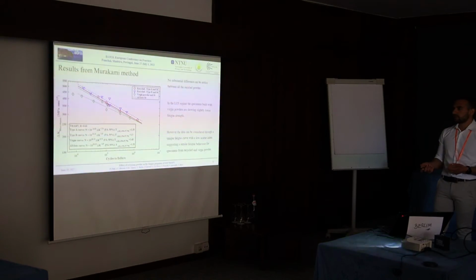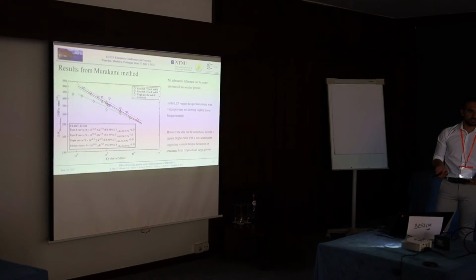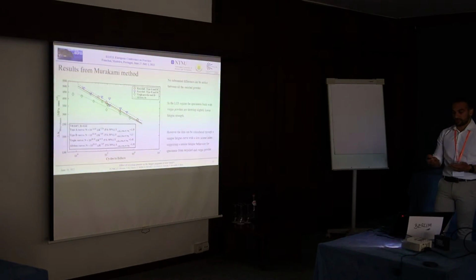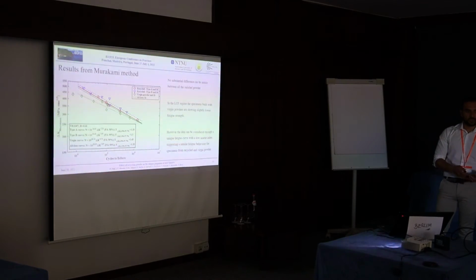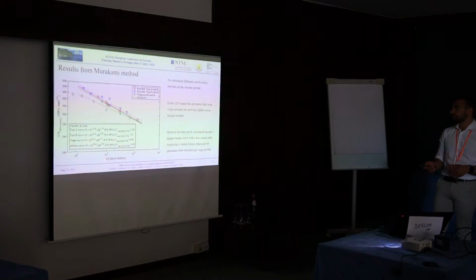And this actually means that we do not expect that the components built from recycled powders and the components built from virgin powders have a difference in terms of fatigue behavior, but of course this is only if we consider explicitly the effect of the defects. However, it is also worth pointing out that for the virgin powder, we have noticed a slight deviation here in the long life fatigue regime that we still need to further investigate.